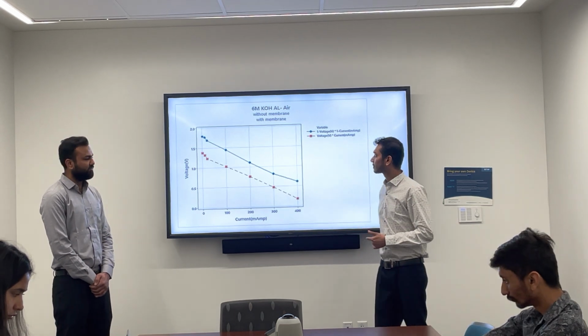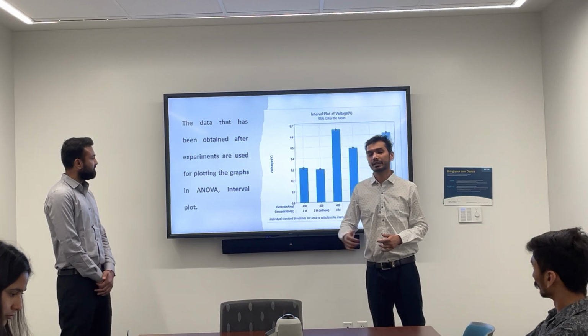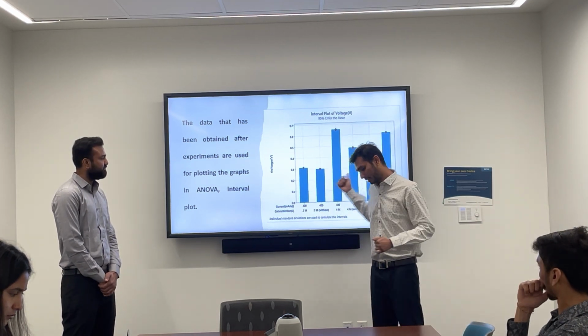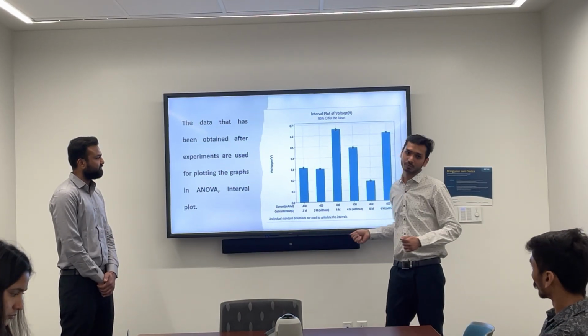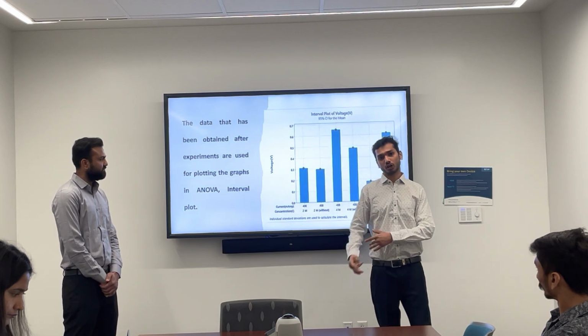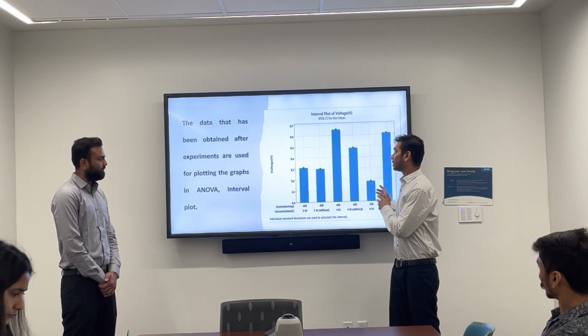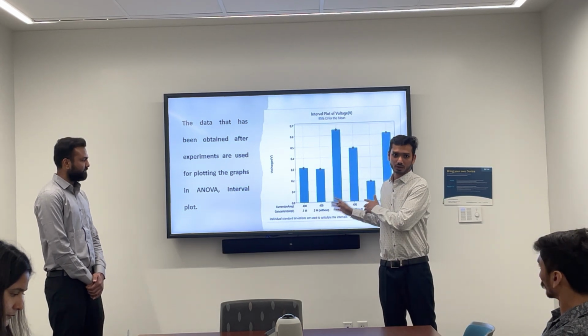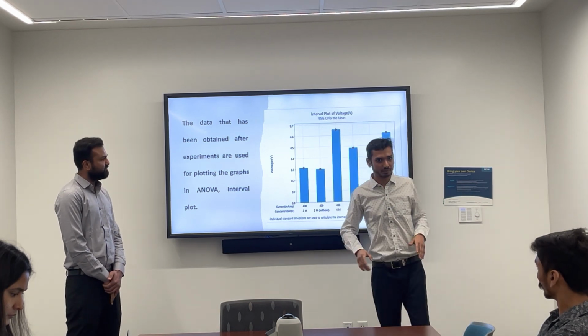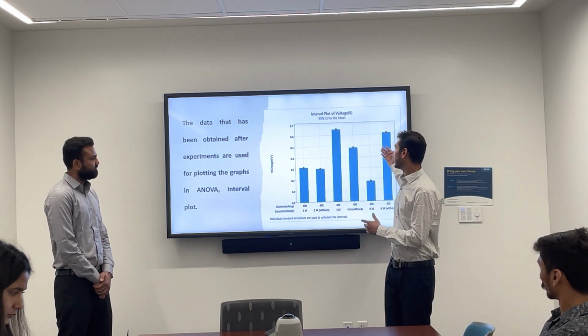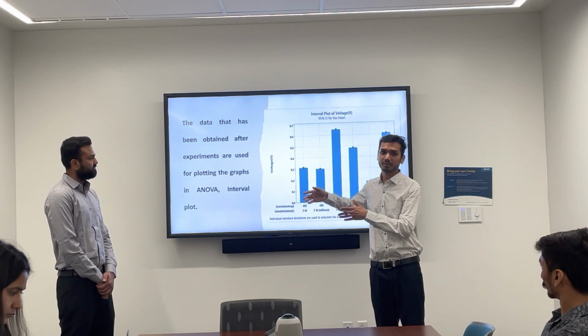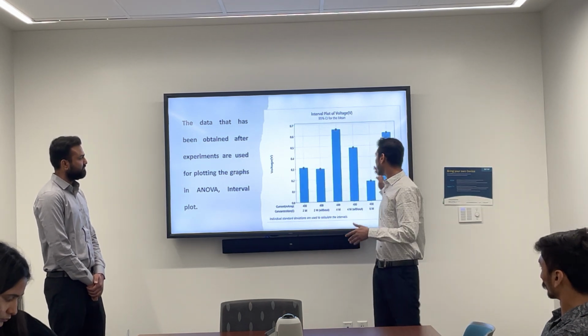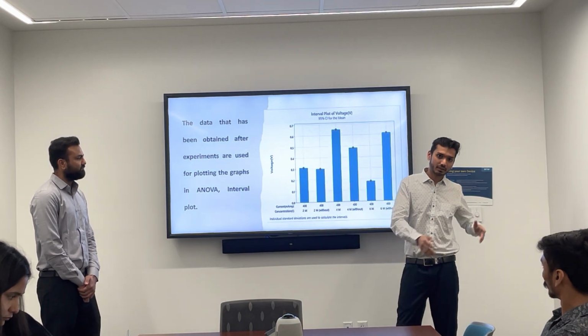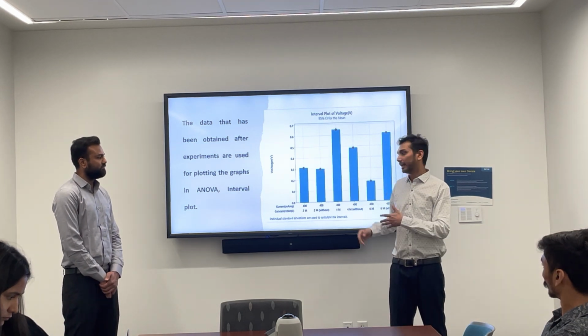Next slide. Here there is an interval plot, and it's for the 2, 4, and 6 molar with membrane and without membrane. This data is only for the cellulose one. We are not proposing any polypropylene one because we made our decision on that. And this data is for the aluminum, but we compared our aluminum and zinc data as well, and it's almost the same.